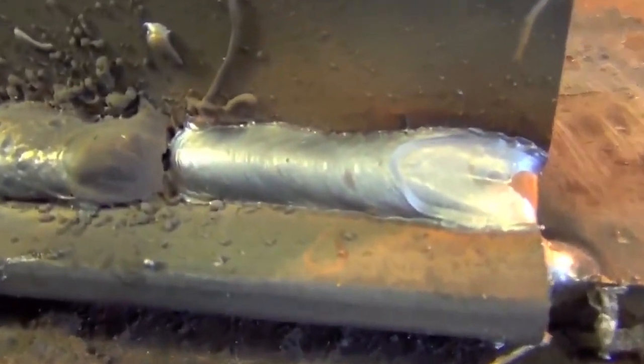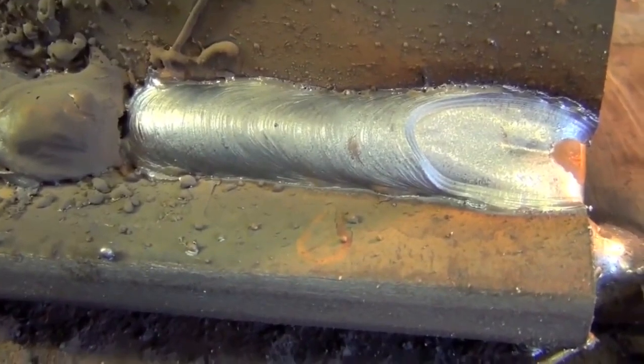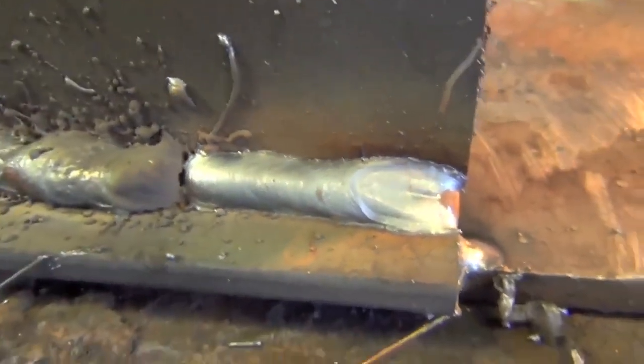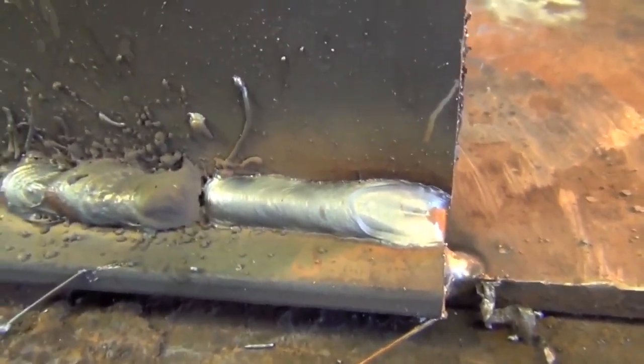As you can see, it's a little bit cold. We still have a little bit of a lack of fusion along that bottom toe line. And I thought there'd be a little bit more spatter than there was, but running too much stick out can cause slightly more spatter. The main thing is, if you have any stick welding background, you'll know that you can control how much heat to an extent goes into your puddle just by running a different arc length.